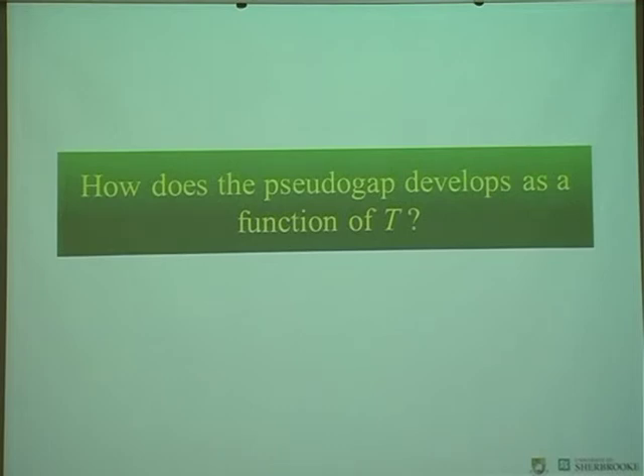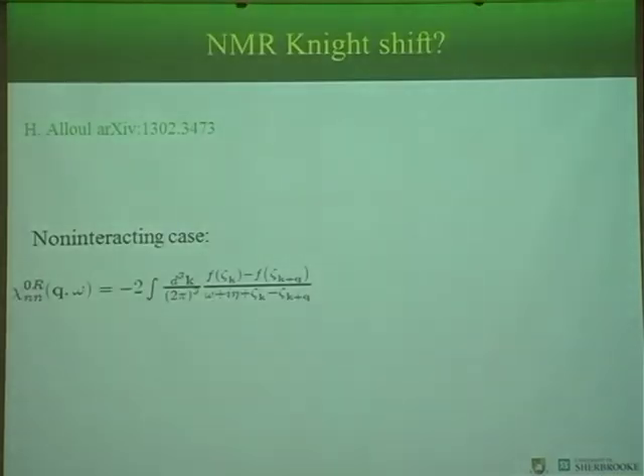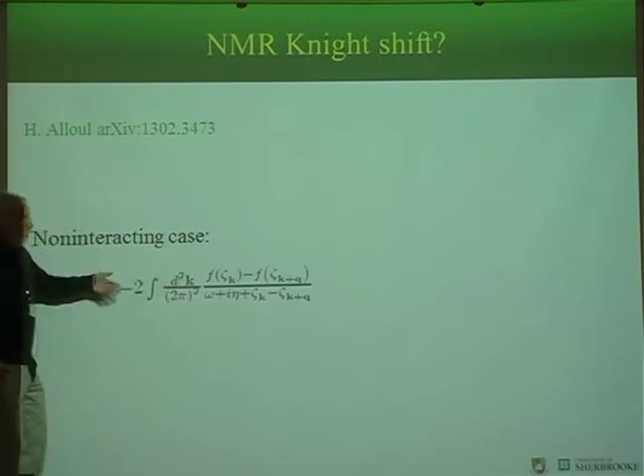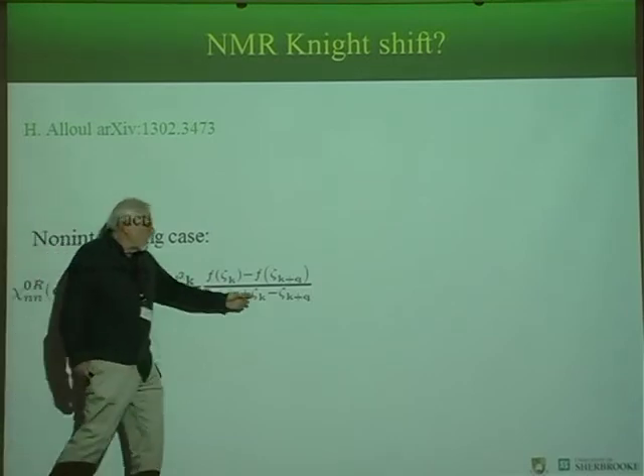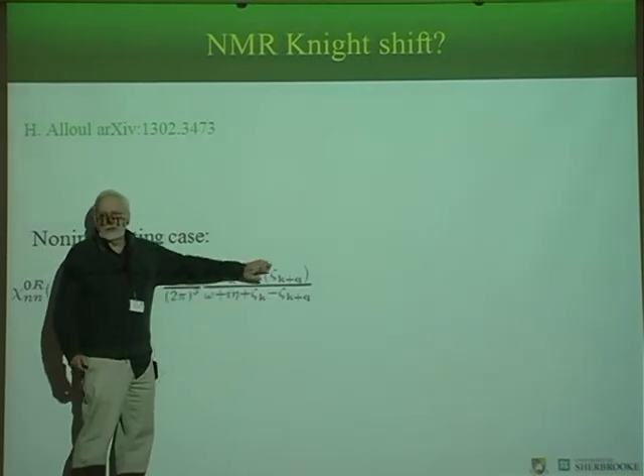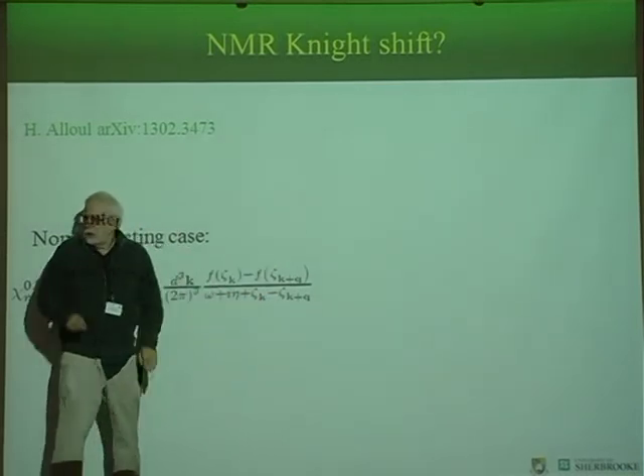strong coupling. And in particular, why it is not a simple precursor can be seen by looking at the temperature dependence as a function of temperature. So this experiment is the Knight shift measured by experiment. So the Knight shift measures the uniform magnetic susceptibility. So if you have a non-interacting system, you can just use the Lindhard function, or if you want, perturbation theory, there's the denominator, and here you just make sure that there's electron and hole.